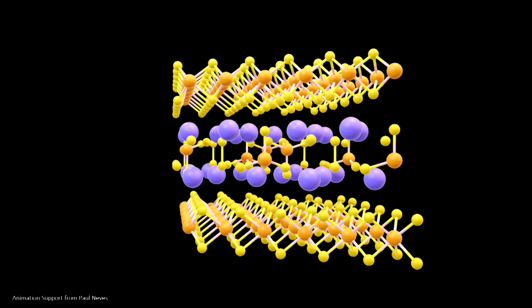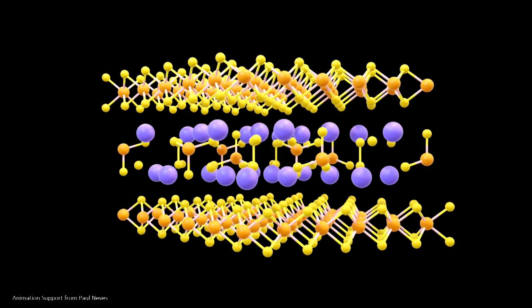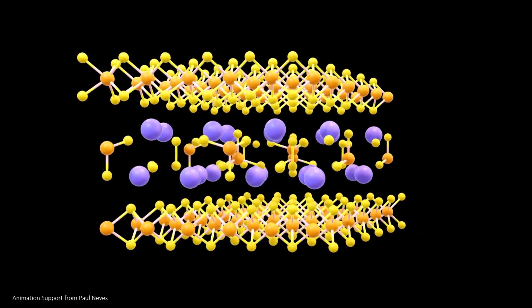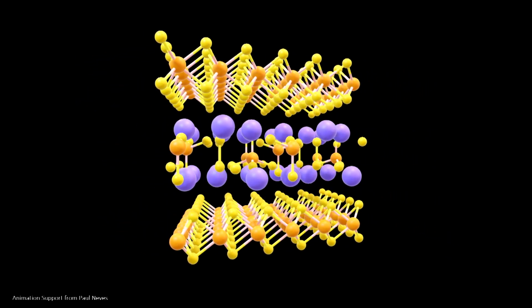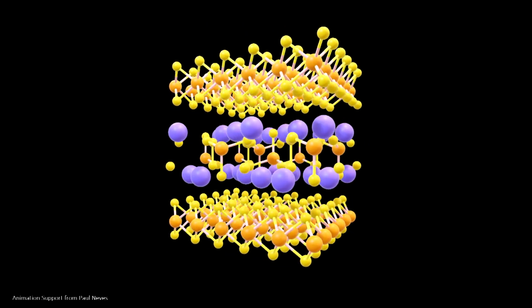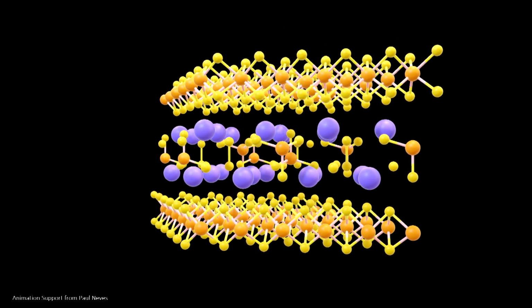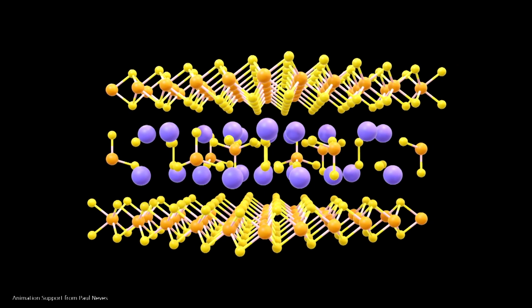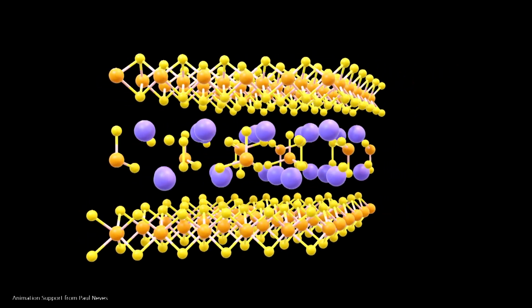But when we incorporate new atoms, these alkali earth elements, they form this layered, ordered structure that separates superconducting layers. So this makes the lattice far more two-dimensional, much more emulating some known structures for unconventional superconductivity. But in addition to that, I have a lot of control over this spacer layer chemically.